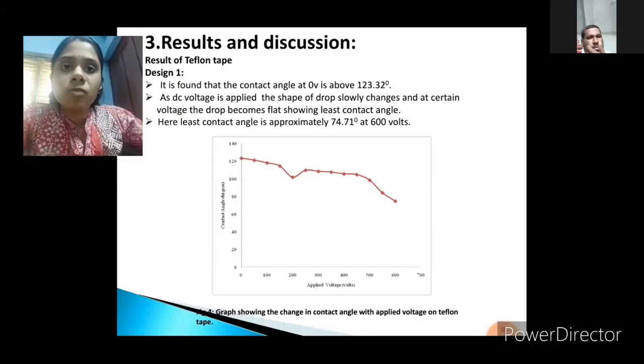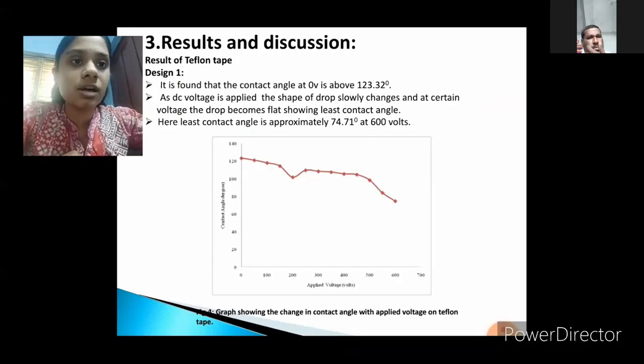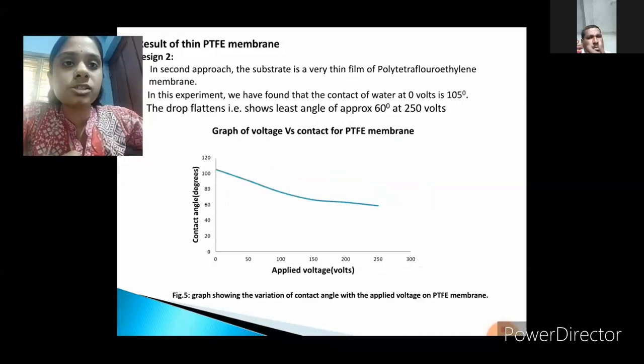Here, the initial contact angle is found to be 105 degrees and the least contact angle is 60 degrees at 250 volts. So, here the voltage requirement has decreased. Now, these are the images that I have captured during the experiment at different volts. We can see the change in the shapes as we go on increasing the voltage.